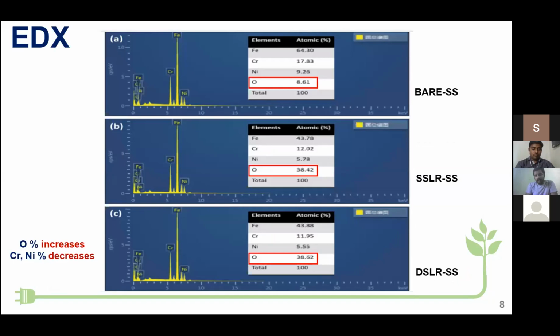So the oxygen percentage is increasing, which reveals that during laser radiation, oxidation takes place. Simultaneously, the concentration of chromium and nickel is decreasing, which shows that the atoms present in the crystalline packing in the bulk get redeposited over the surface and undergo oxidation to multivalent oxides.